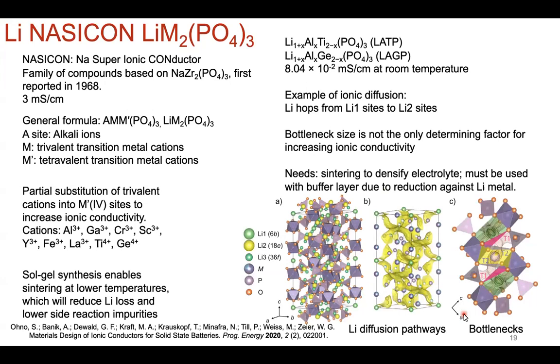Okay. So in looking more within the LISICON style family of compounds, we also come across the NASICON, or sodium superionic conductor, as its acronym stands for. And so here, the goal is, same thing, to introduce substitutions and introduce site disorder to increase the ionic conductivity. And so the cation site within this generic formula, you have your alkali ion site, and then you can have a trivalent transition metal cation, and then a tetravalent transition metal cation, and then some combination in between the two end members of the pseudo-binary phase diagram. You get the middle, and then the ionic conductivity increases.